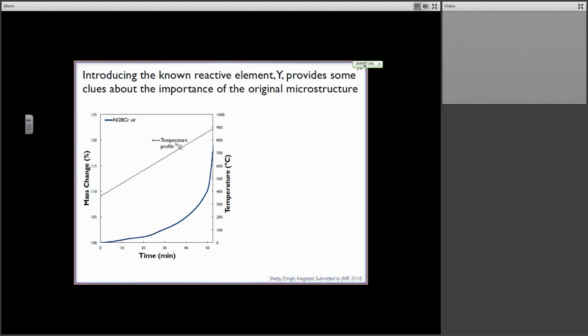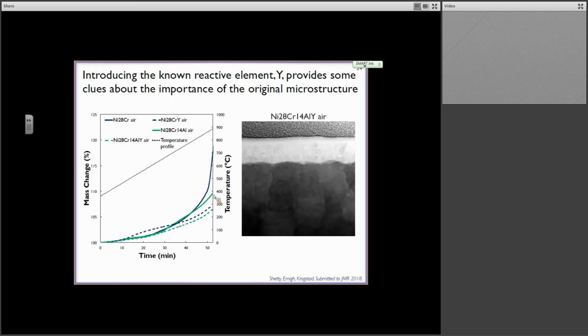And then we put it back through the same rigor of tests that we had before. So this is the same data I showed you earlier with the spiky oxide that was forming. This is just nickel chrome. If I add aluminum to the same ratio of nickel and chromium, I have a lower slope and a lower point here on this plot, which suggests it has better oxidation resistance. That makes sense with the rules that we laid out. Higher aluminum concentration, higher oxidation resistance.